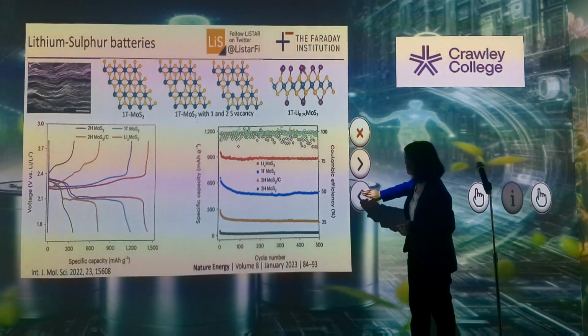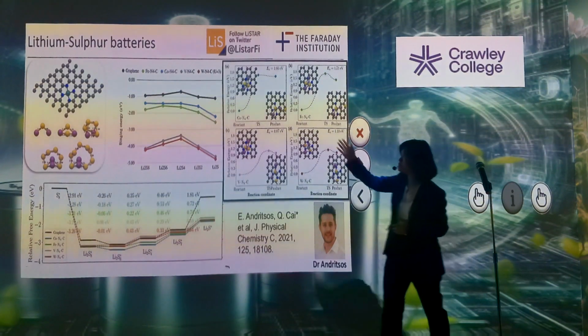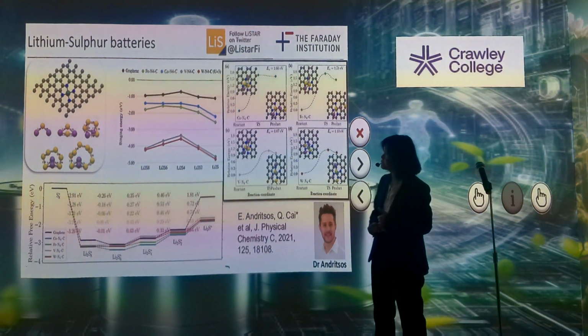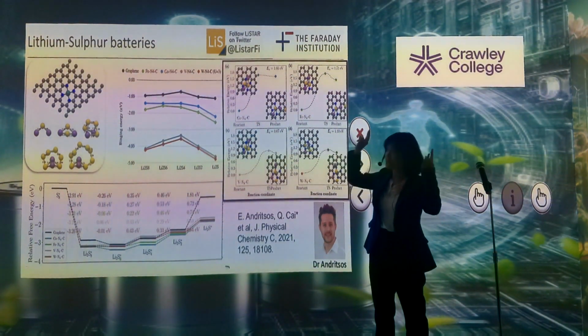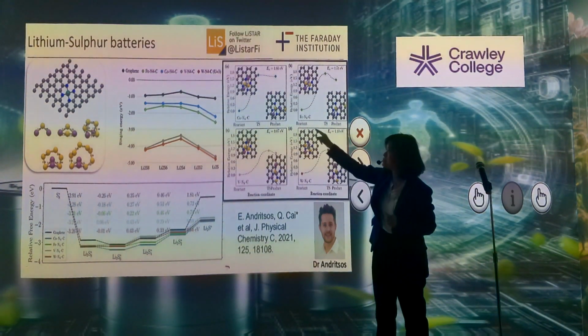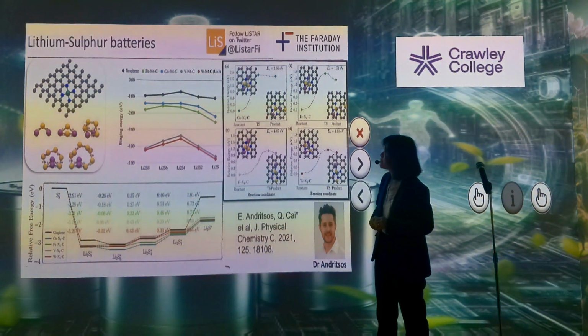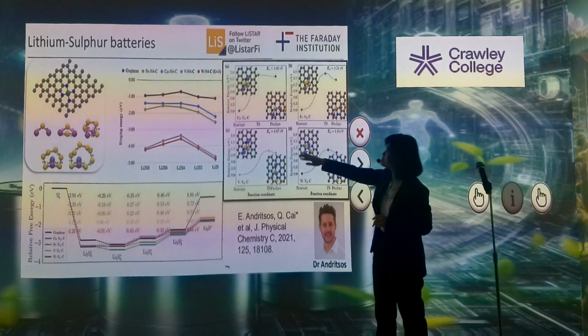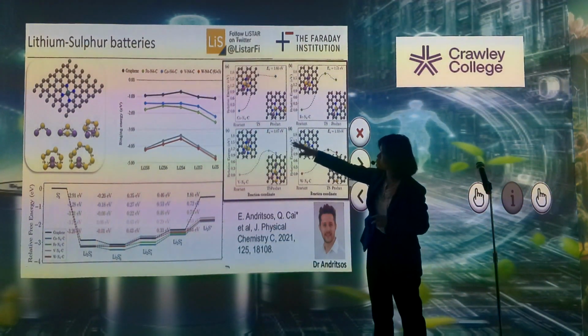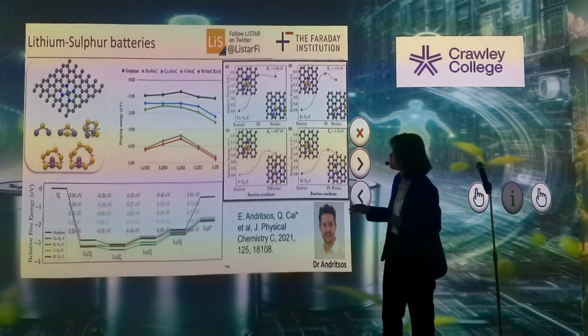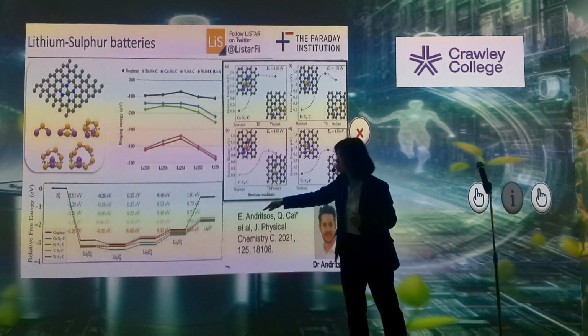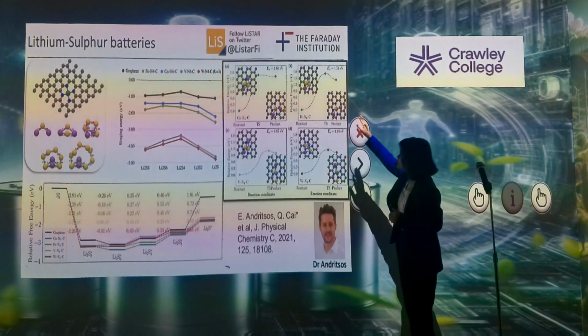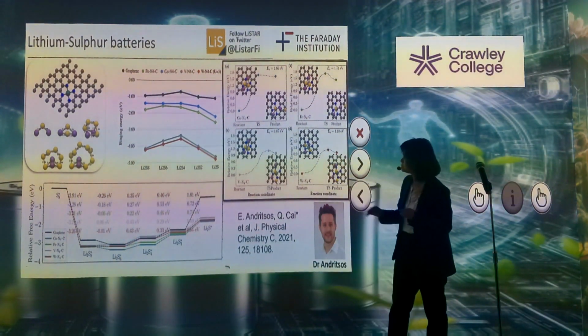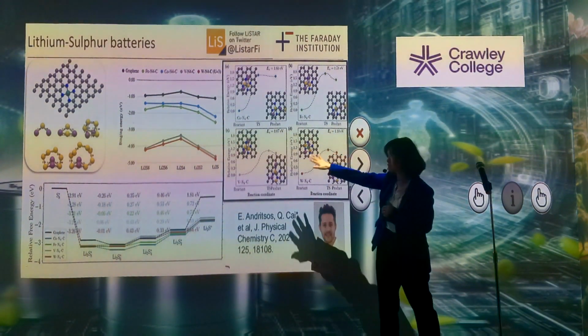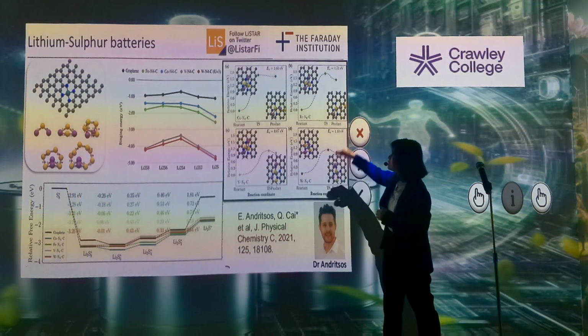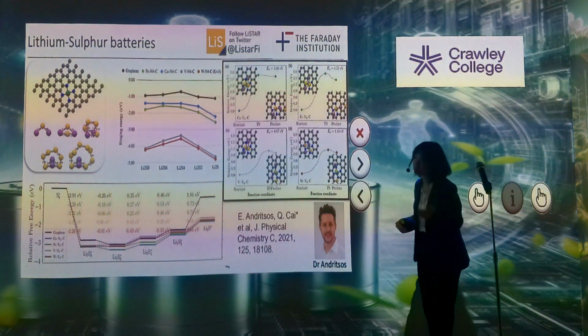So one of the materials we proposed is called single atom catalyst. Basically you have a transition metal as the active site sitting in a carbon matrix, carbon lattice, surrounded by 4 nitrogen atoms. What we found is the vanadium and tungsten-based ones give very strong binding energy for the polysulfide molecules. Therefore, we think they should be able to trap the polysulfide molecule there. We also looked at the reaction pathway for the polysulfide molecule conversion, and also the activation barrier for the conversion. And we found that, again, the vanadium and tungsten-based ones provide lower activation barriers, meaning that they will be able to speed up the reaction process.